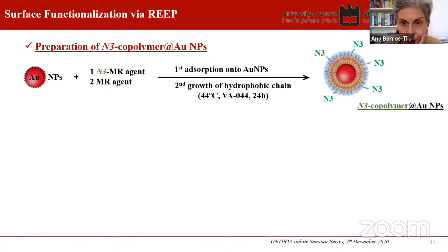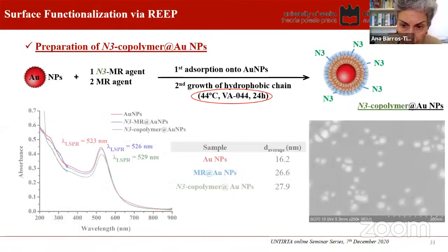So once we added this azide group, we had to be very careful and adapt to the polymerization conditions. So we actually had to change initiator and work at much lower temperature because, as you know, azides are groups that are very dangerous and can lead to explosion reactions. So we had to study all the conditions again to adapt to this new initiator.